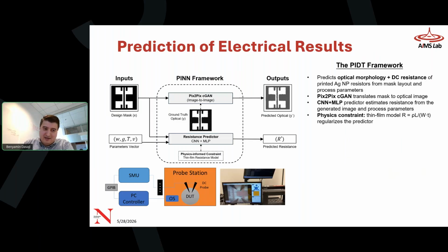For this, we need to add a layer of measurement where we need to measure devices automatically. If you have a flying prober, that's fantastic, but we kind of modified a semiconductor automated prober, and we learned a lot. For example, these sheets are not staying flat, especially for polyimides after sintering. So we had to learn a few tricks how to get things correctly. And also we need to buy basically the largest radius of curvature probe so it doesn't poke through the cured ink.